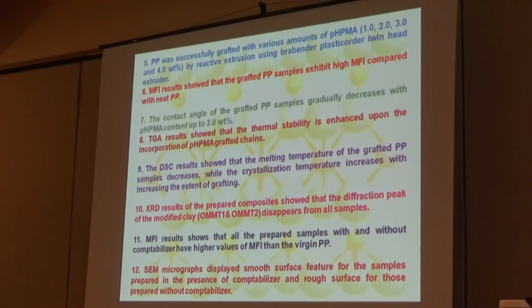The contact angle of the grafted polypropylene samples gradually decreases with p-hydroxy-N-phenyl maleimide content up to 3%. TGA results show that the thermal stability is enhanced upon the incorporation of p-hydroxy-N-phenyl maleimide grafted chains. Differential scanning calorimetric results show that the melting temperature of grafted polypropylene sample decreases while the crystallization temperature increases with increasing the extent of grafting.